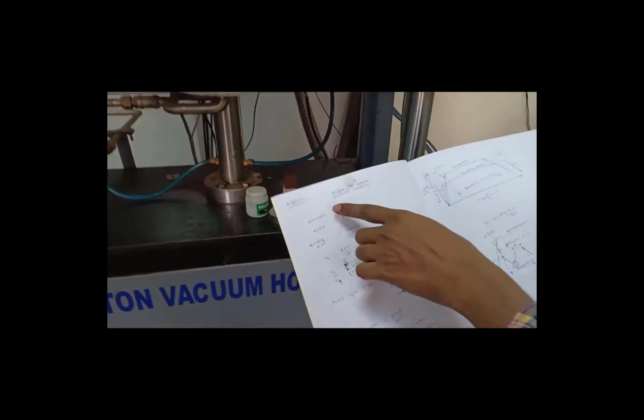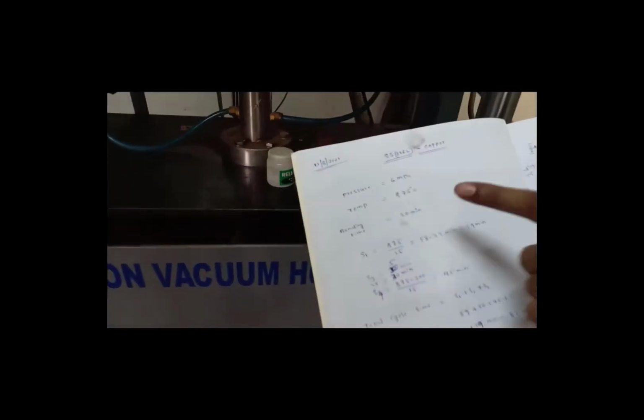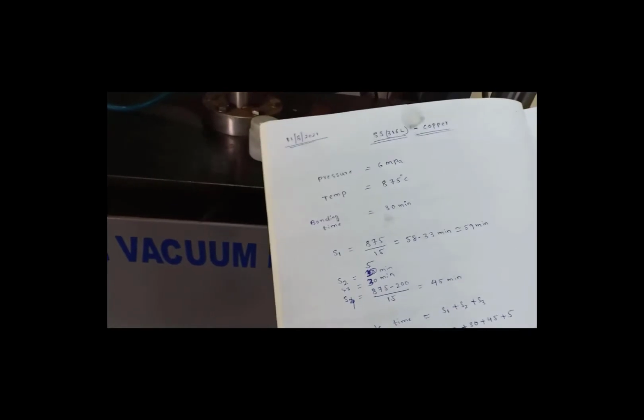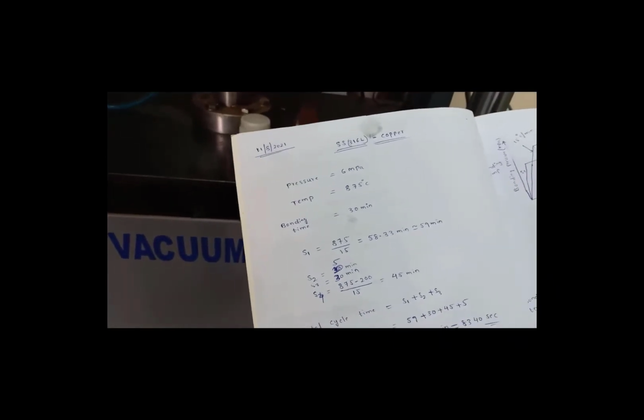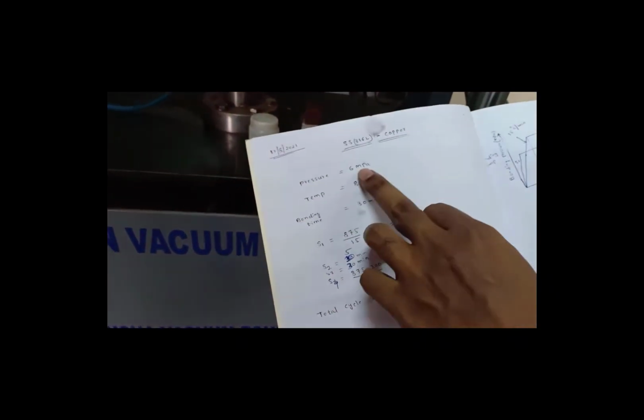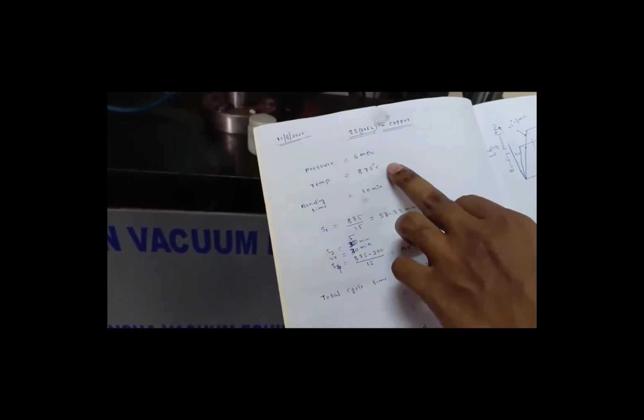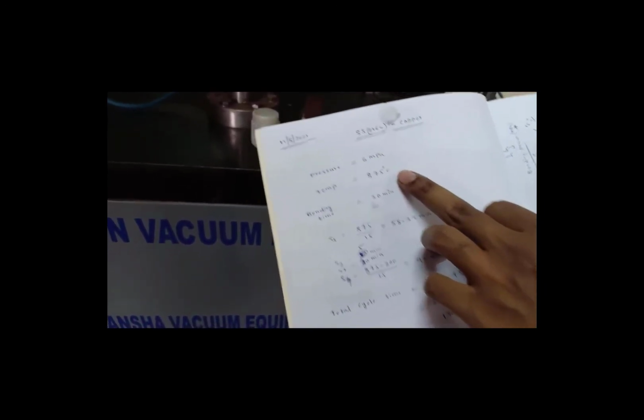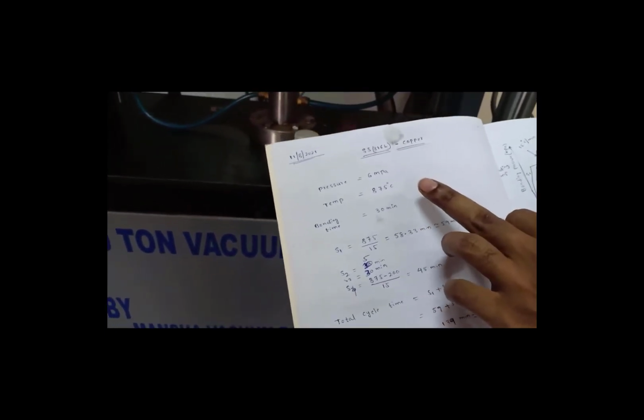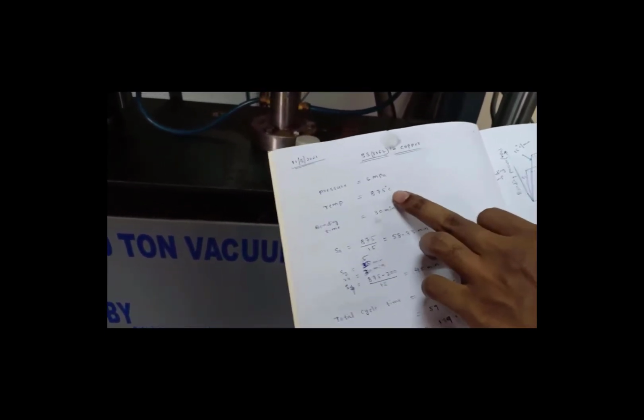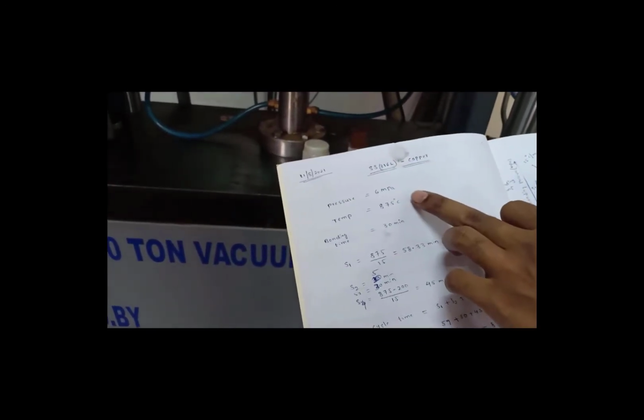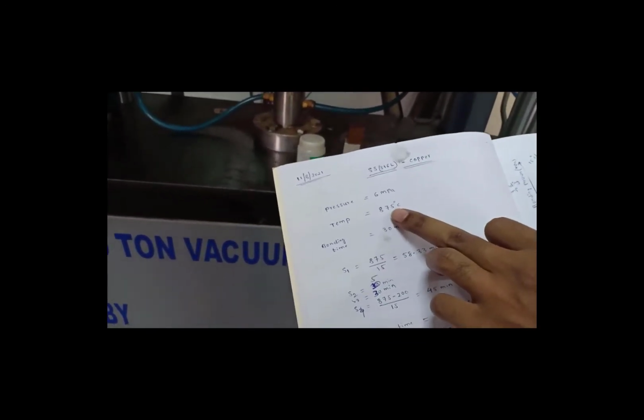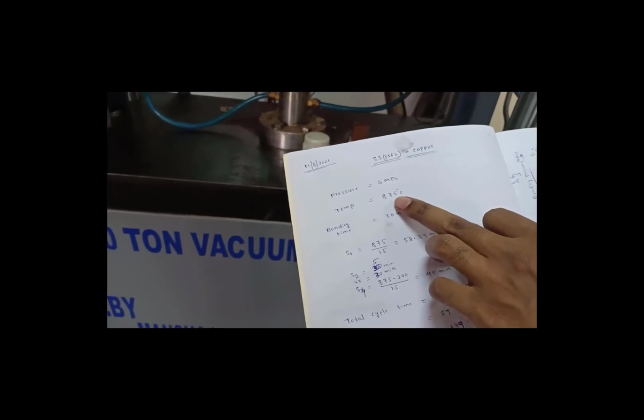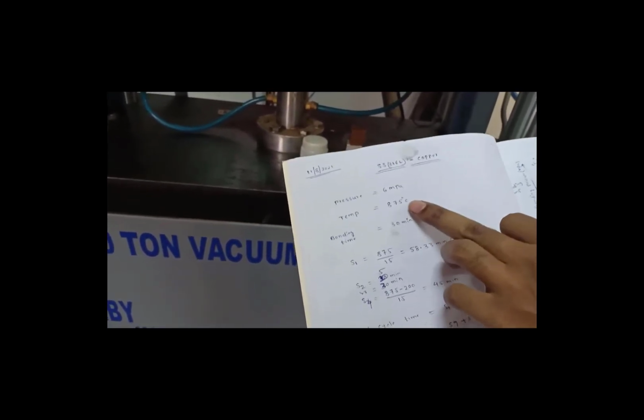This is the setup of the parameters for performing the diffusion bonding. For stainless steel and copper, we are considering a pressure of 6 megapascals and a temperature of 875. The temperature is generally controlled at 0.5 to 0.7 of the melting point. Based on these two, we consider the lowest one, that is 0.5 to 0.7 TM, the melting temperature.